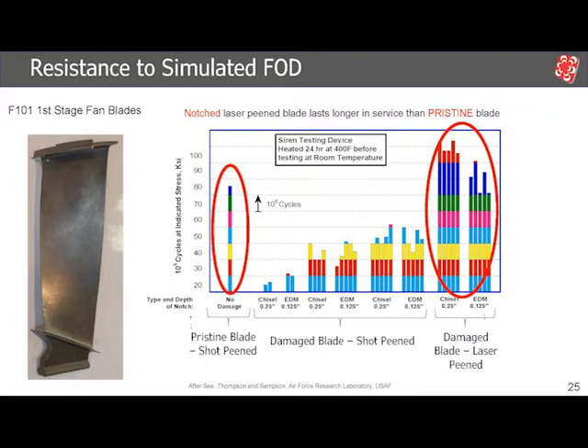And trying different types of shot peening was able to recover some of that life, but it's nowhere close to where the actual life of the pristine blade is. That's where laser peening was investigated, as you can see here. Even the notched blade was able to perform equivalent or even better than the pristine condition of the blade.